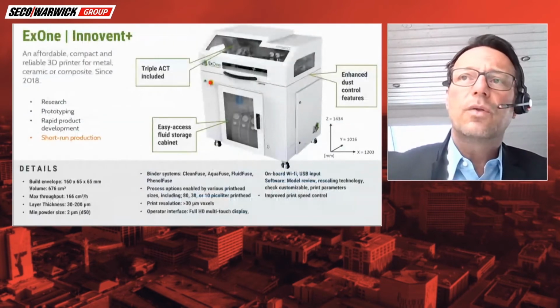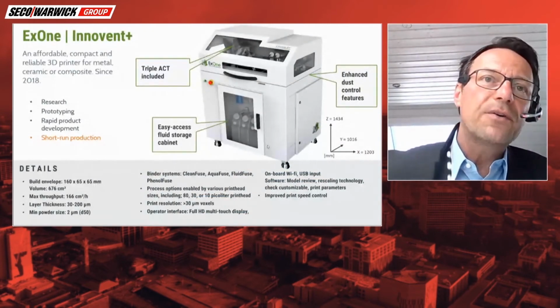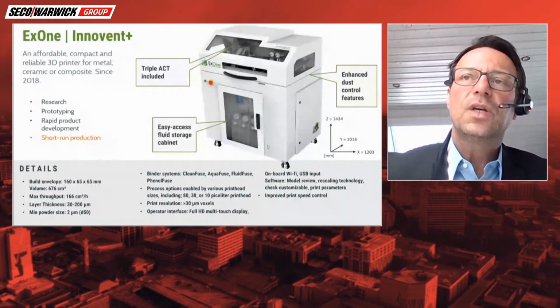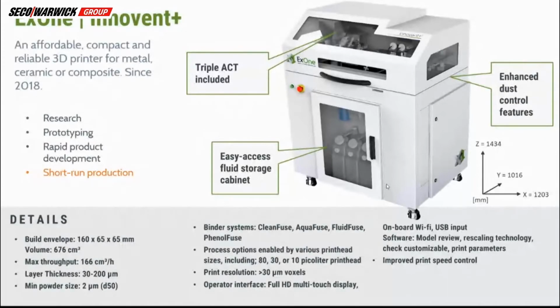Let's have a quick look at the machines as such. The R&D machine, we call that Innovent Plus. It has a small build room, but most of the time enough build room to make a small part, to do the first tests, to do the development work with one or the other material. And the nice thing here is that you can change over the materials quite easily. If you go for an iron-based alloy, or you want to change to a nickel-based one, you can change with a clean time of less than 2 hours.